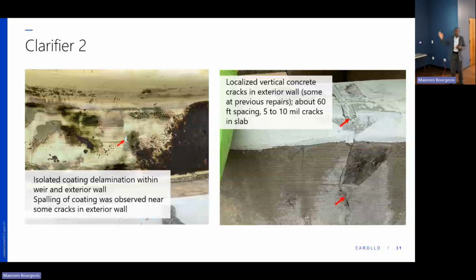So summary of the petrography there we talked about. And then as far as the deterioration of the concrete on the surface of the cores, it was very minor compared to the rest of the structures. So again, similar recommendations, visual assessment 3 to 5 years, non-destructive and lab testing every 10 years.